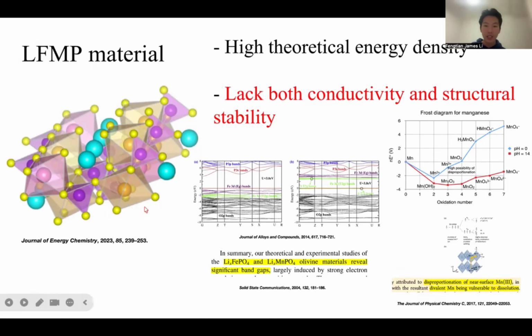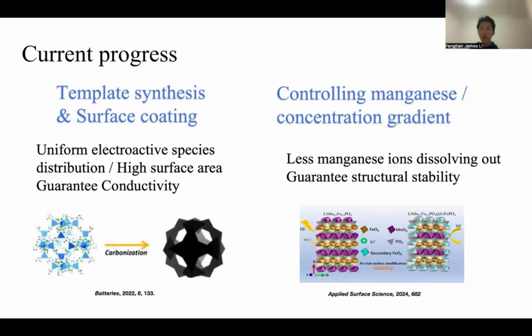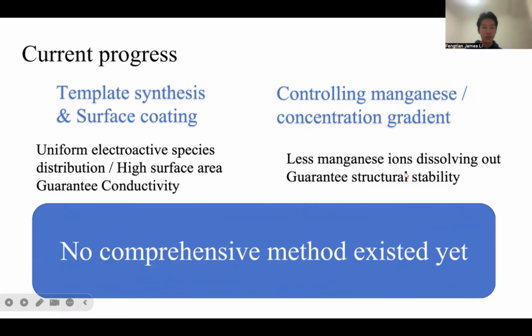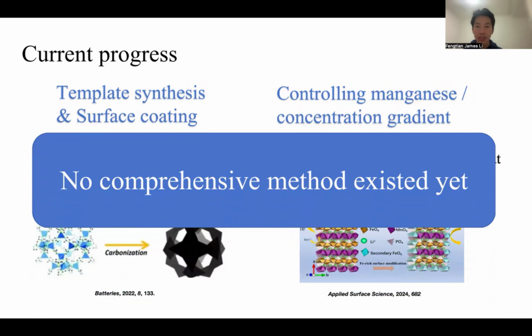The lack of conductivity comes from its electronic structure as well as crystal structure, while the lack of structural stability stems from the Mn3+ ion within this bulk material, which will disproportionate into Mn2+ and 4+. The 2+ ions will then dissolve into the electrolytic solution, causing the whole structure to collapse. The current progress on solving this issue is not comprehensive. They either guarantee conductivity or structural stability, but there's no comprehensive method existing.